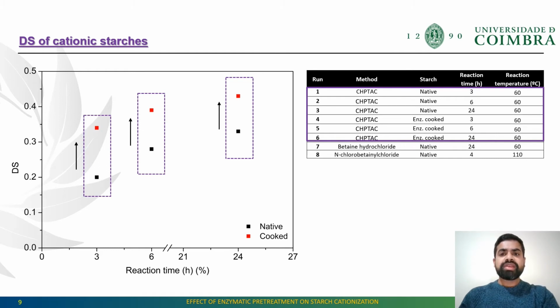This increase is likely due to the formation of more porous starch granules, which facilitates the access of reagent to the hydroxyl group of starch. It was also observed that the cooking of starch enables the homogeneous dispersion of starch granules in the solvent by increasing the solubility.